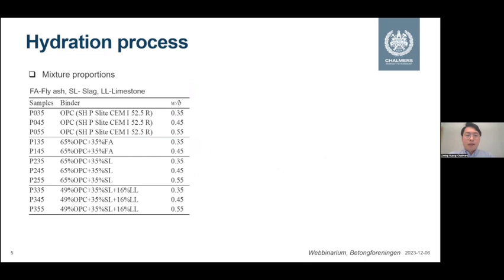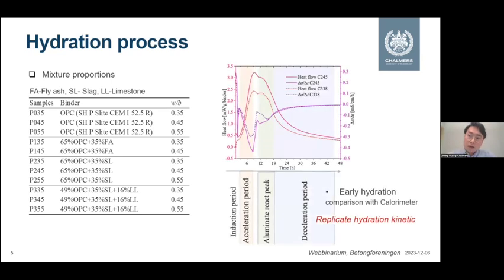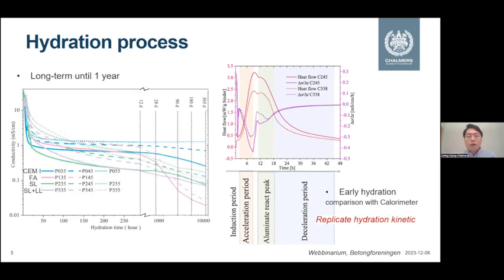To validate this test system, we have cast 11 samples using the same cement with 3 different water-to-binder ratios. For the SCMs, we have well-used types like fly ash, slag, and limestone as filler in the P3 series. If we look at the early age hydration process, we can see that it can really replicate the hydration kinetics, as shown here in comparison with the isothermal calorimeter test. We can reflect the silicate reaction peak and also the aluminate reaction peak.